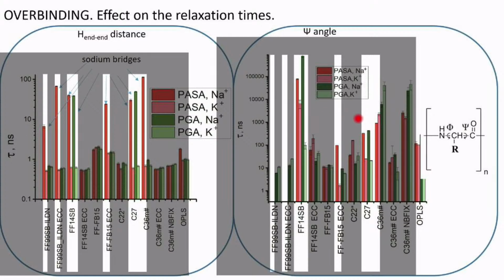But in the case of, for example, CHARMM 36, the relaxation time of this angle is higher in the case of potassium ions. So when you have overbinding in your system, the results could be unpredictable when we are talking about local change of the local structure of the chain.